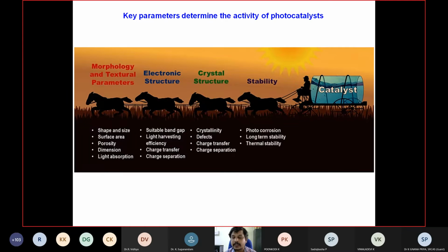If you have a spherical catalyst, that will have some efficiency. Suppose you make a porous material, the electrolyte can penetrate inside, and that will increase the performance of the photoelectrochemical activity. Likewise, if you tune the band gap, the band position will be shifted, and then the region of light absorption also changes. So the electronic structure is important. Likewise, crystal structure: if you create a defect or something, then you can improve the charge transfer process. So that also plays an important role.